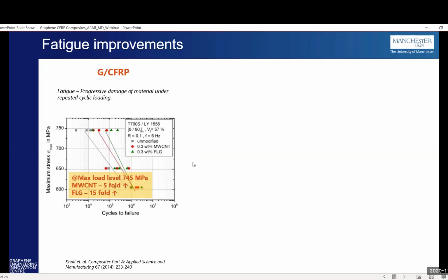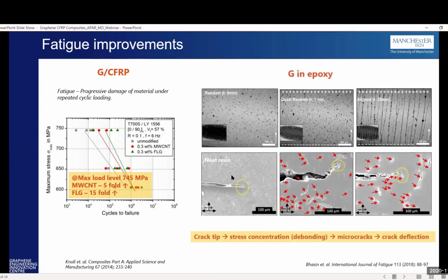This can be easily explained in this study where graphene is used in just an epoxy itself. This is a pretty neat study in which they distributed the graphene in the resin using different dispersion techniques. And they applied an electric current to see if they could align the graphene in the direction of the electric current. As you can see, they have actually achieved it. And these samples have gone through fatigue testing.